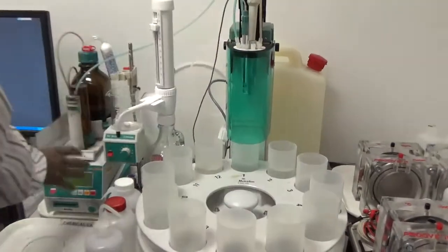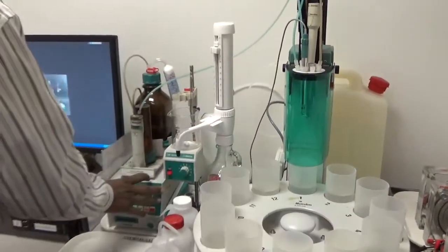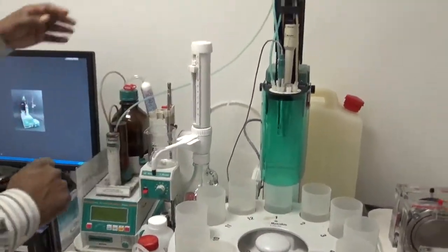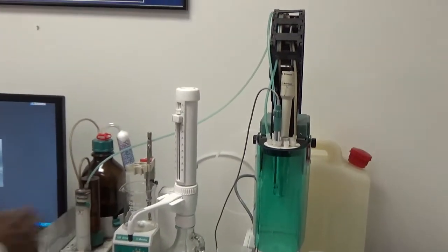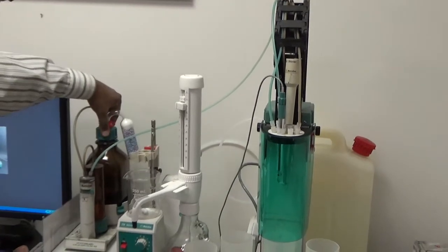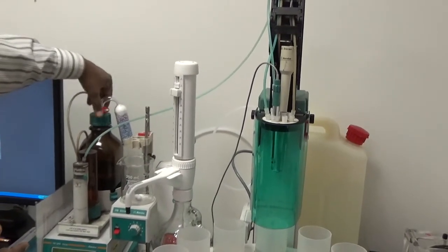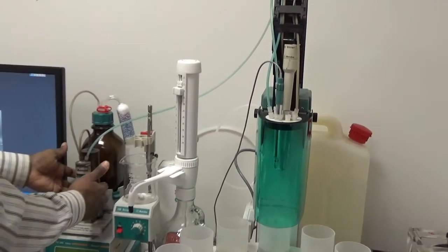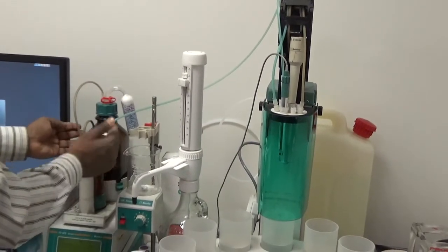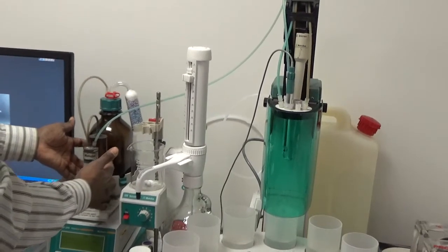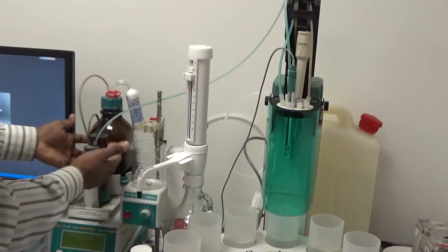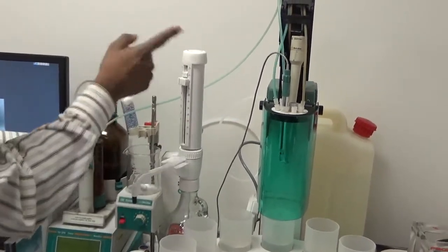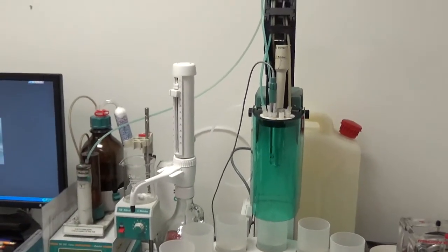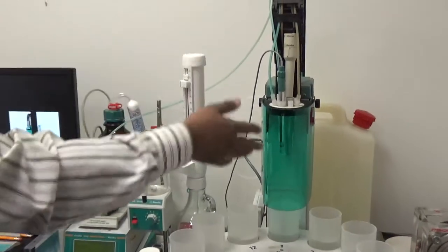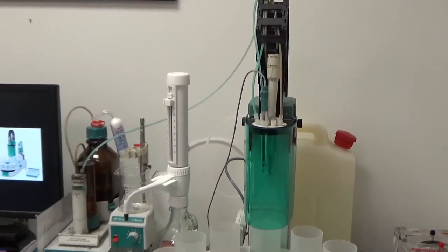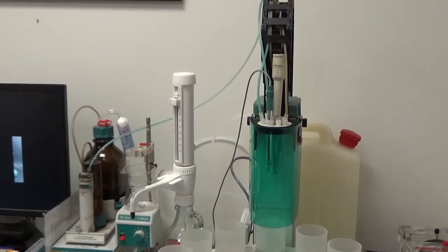The rod stirrer is connected to the Titrino, the metal electrode is connected to the Titrino, and the burette through which the silver nitrate titrant comes is connected to the stopcock of the exchange unit. When the titration starts, the silver nitrate comes from the main bottle, a 1 liter amber bottle, to the middle cylinder. The middle cylinder is a 5 milliliter volume of silver nitrate. The titrant comes from the main bottle to the middle cylinder, and then there is a piston. The piston goes up in increments and dispenses 0.2 milliliter of silver nitrate every time. So it's a very controlled dosing mechanism by which the piston brings a little silver nitrate to be added to the solution. Every time we do chloride analysis, we use the silver nitrate as a titrant to determine the chloride content.